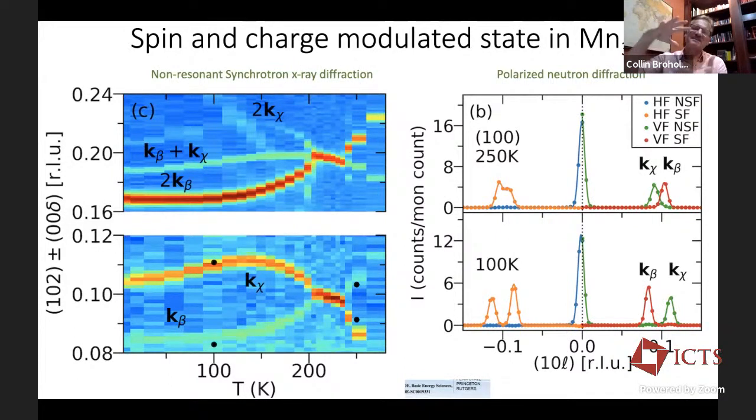So essentially, just in a snapshot, in the commensurate state you have this anti-chiral state on every Kagome layer, and those are actually oriented in the same way. If you will, the ferromagnetic moment is oriented in the same direction. But in this incommensurate state, the ferromagnetic moment and the entire anti-chiral state actually begin to rotate as you come along the c-axis. And we see that in the magnetic diffraction, both of synchrotron X-rays as well as polarized neutrons.